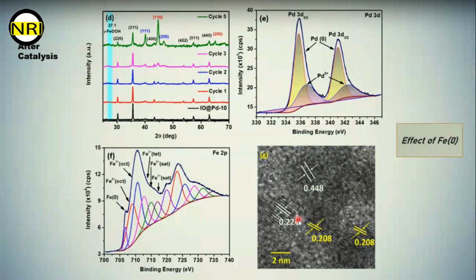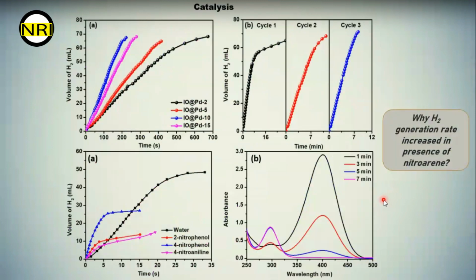So all these characterization tools prove that iron 0 is formed during this hydrogen generation reaction, and this iron 0 stays at the Fe3O4-Pd interface. For any catalysis reaction, the metal oxide interface is very important. If we can modify the metal oxide interface, we can change the catalytic activity. So in our case, maybe this in situ synthesized iron 0 has some synergistic effect with the palladium, and that is why the rate of the reaction for the hydrogen generation as well as the tandem reaction is increased.